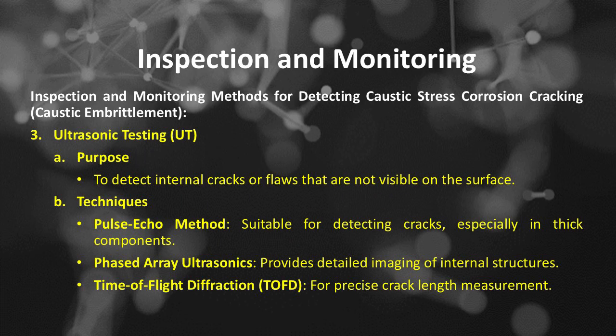Number 3 is ultrasonic testing or UT. UT purpose is to detect internal cracks or flaws that are not visible on the surface. Here are a few UT techniques that can be used to detect caustic embrittlement. Includes Pulse-echo method, suitable for detecting cracks, especially in thick components. Phased array ultrasonics provides detailed imaging of internal structures. Time of flight diffraction or TOFD for precise crack length measurement.